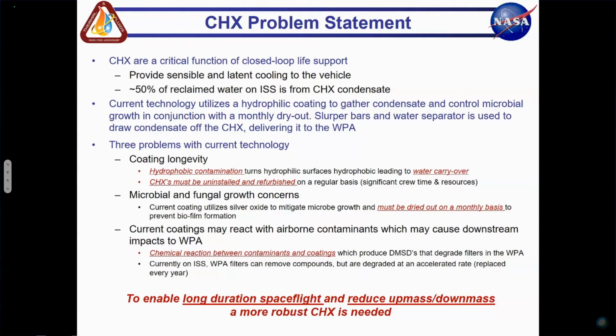There's 3 big problems with the current technology. One is coating longevity. Hydrophobic contamination causes that hydrophilic surface to turn hydrophobic, and you get water carryover, so water spits out of the heat exchanger and potentially damages downstream components. Because of that, your heat exchanger ORU has to be uninstalled, brought back down to earth, refurbished, and then sent back up. That's a very significant resource drain. Second concern is microbial and fungal growth concerns.